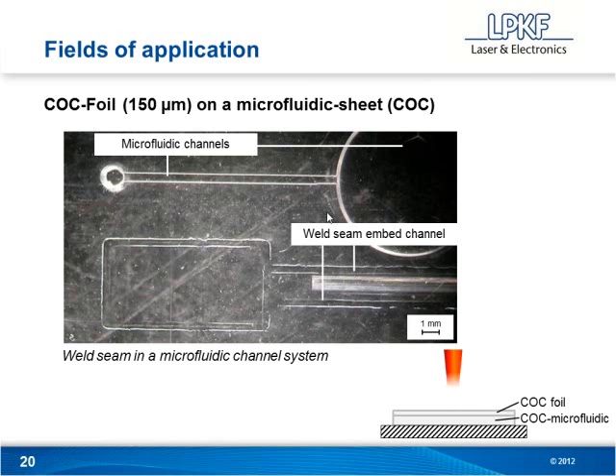And what's happening is as the weld is taking place, you're left with these reliefs or these channels. And it does a very nice job of this. That's because the laser doesn't necessarily have to travel perfectly on the outside of the channel. We can actually overlap it a little bit, and you still have this nice clean edge where the channel takes place because we don't have any absorption at that point. So it works out very well for microfluidics and very fine microfluidic devices.